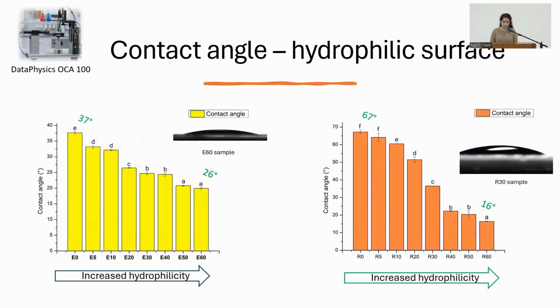The last analysis was the contact angle. The first one was on the hydrophilic surface. For ethylene glycol, we see a decrease of the contact angle from 37 to 26, meaning an increased hydrophilicity. Also, an increased hydrophilicity with the increase of water was seen in the case of Reline, but with a faster step.